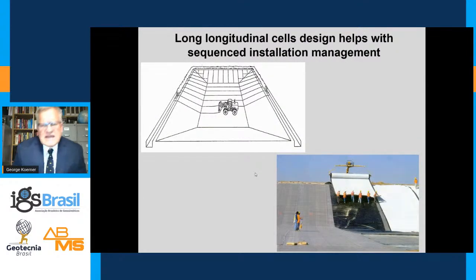You are helped tremendously in the installation by a good design. And what I mean by that are typically long longitudinal cells. Here you see it in schematic. You also see it here. These systems become complex. Here is a composite liner system of a GCL in gray, a geomembrane in white with black edges. This sheet is a rub sheet, and it's textured geomembrane, so it would bite into the needle punch nonwoven significantly. They're going to deploy the geomembrane and then pull this rub sheet out like a Houdini trick on a tablecloth. So you need to know the installation procedure and certainly have to be cognizant of it going forward if you want to be expeditious on your installation.